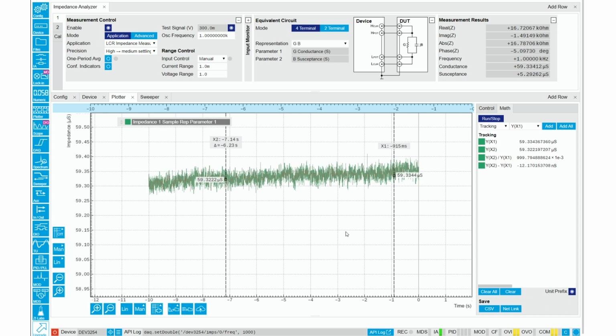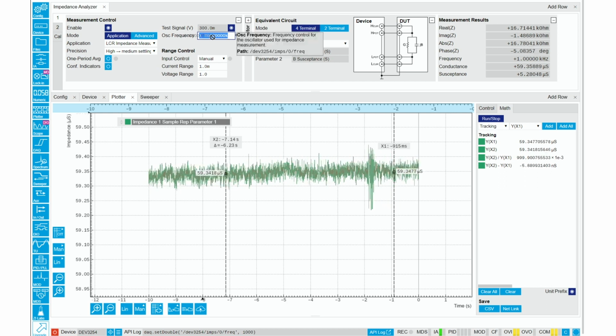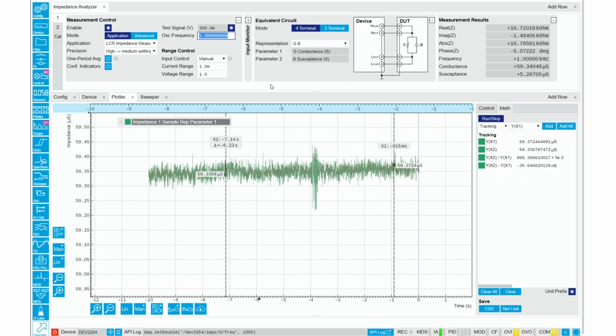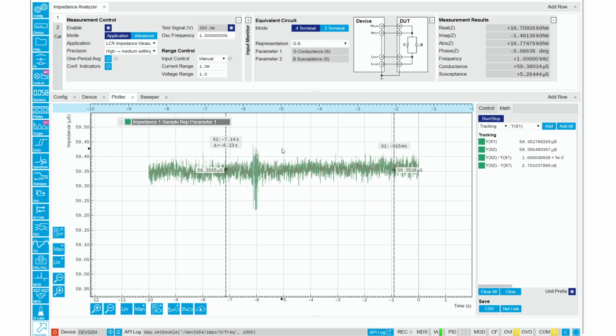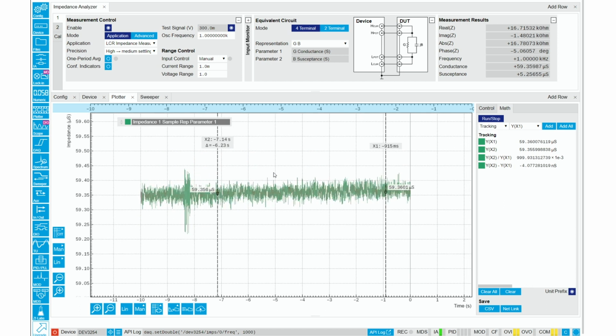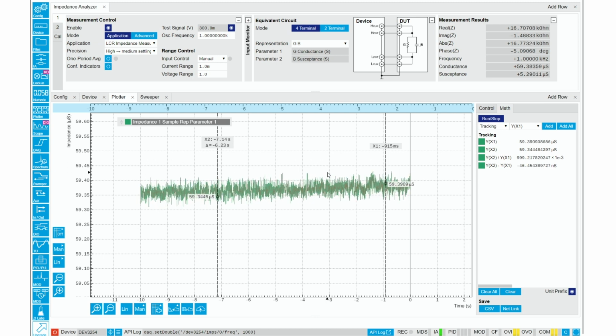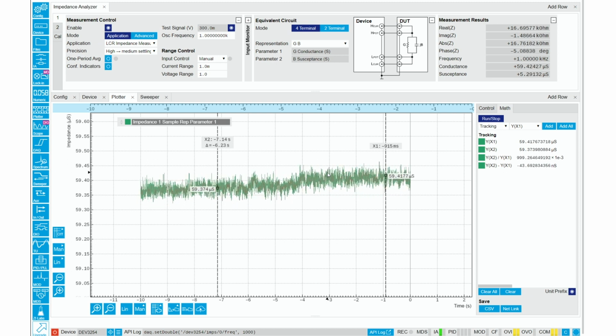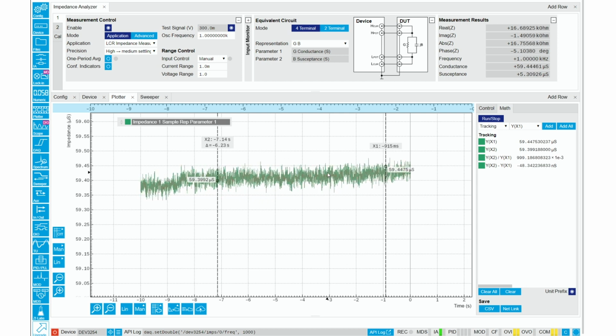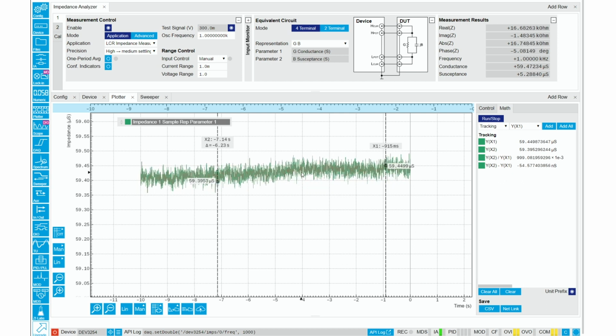Typical probes have a characteristic frequency at 1 kHz, so if we set the MFIA frequency here, we can then just measure the impedance of this conductive liquid and monitor how it changes over time. Dividing the measured conductance by the cell constant gives us the conductivity in the unit of Siemens per centimeter. However, note that there are also other circuit elements, such as double layer capacitance, in this circuit. As such, this probe cannot be used for accurate loss measurement.